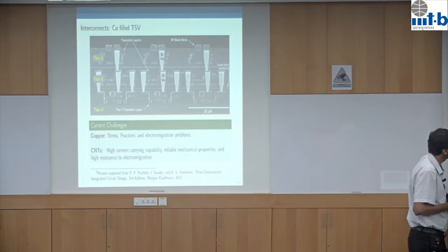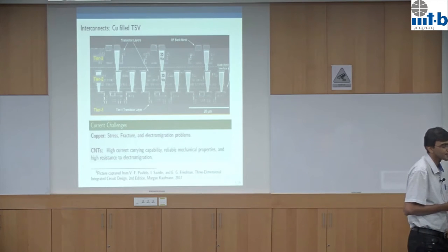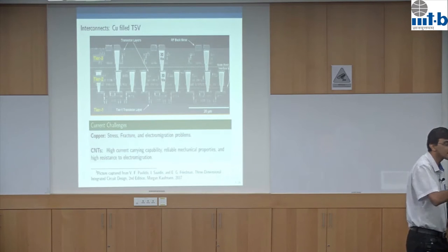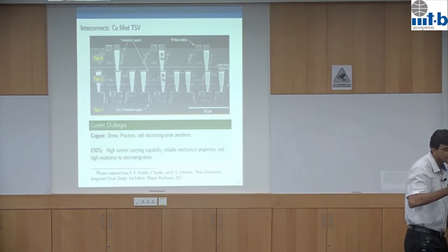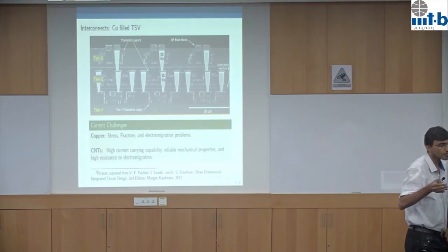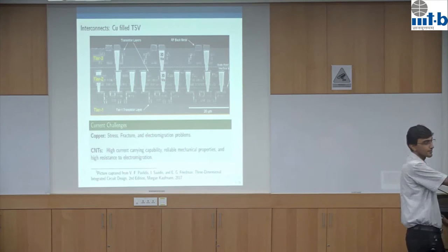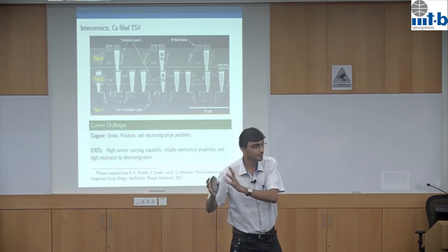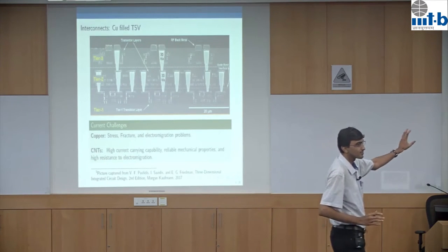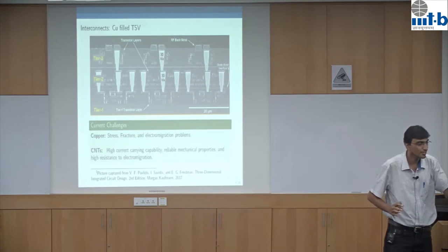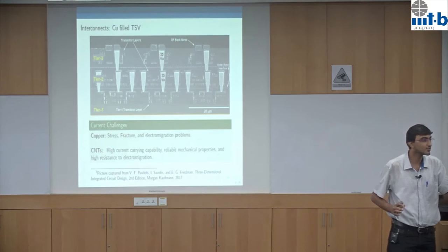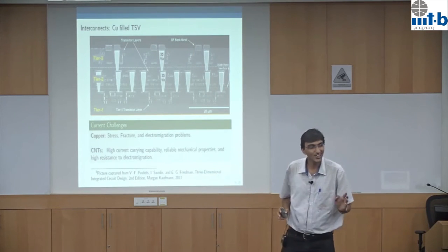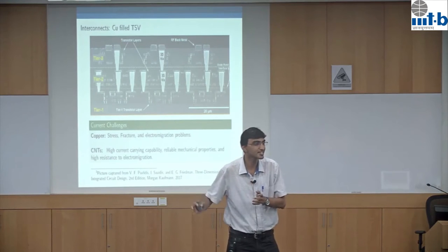I think silver also has this electromigration problem. Silver, aluminum, in fact aluminum was a better material, but filling up silver and aluminum, as compared to copper, the deposition technology is not as smooth as that of copper. So the IC industry finally went to copper deposition via the plating process, as compared to silver and aluminum. I think there is electromigration as well as some kind of a voids problem in the aluminum as well as the silver. Yeah, gold is probably better. Gold plating is also very standardized, but I think it's very, very expensive.